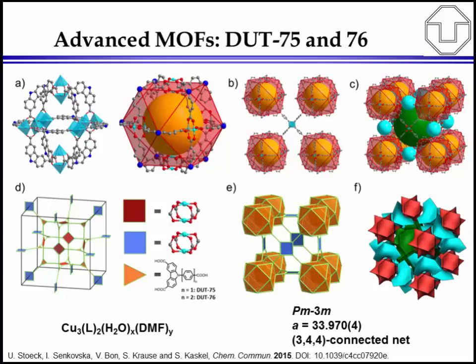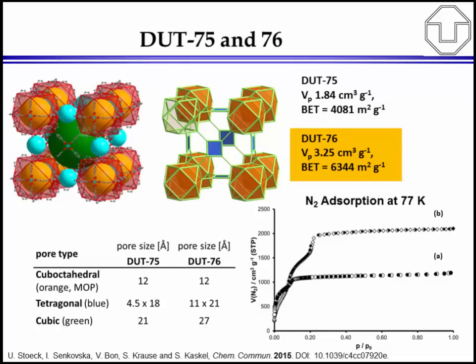And in the next slide, you can see some of the physisorption data on the right hand corner, right bottom. You see the typical nitrogen adsorption isotherms. Here we have achieved a record, a very high BET surface area, 6,300 square meters per gram. Also a very high pore volume, 3 cubic centimeters per gram for DUT-76. And you can see that for DUT-76, the large pores, the cubic pores, which are shown in green, are 27 angstrom in diameter, so almost 3 nanometers in pore size.